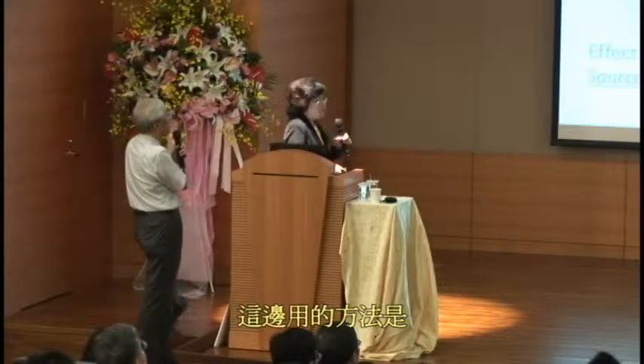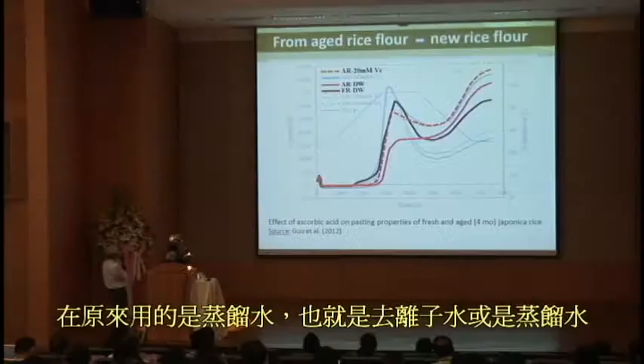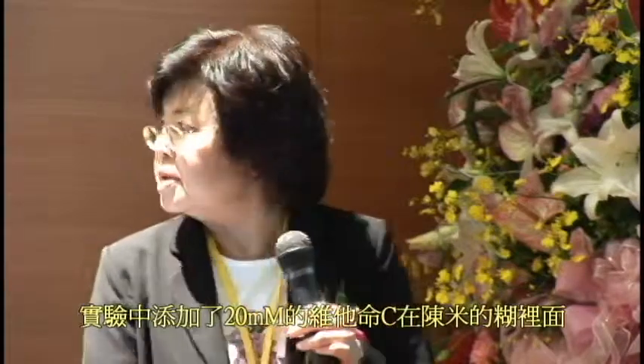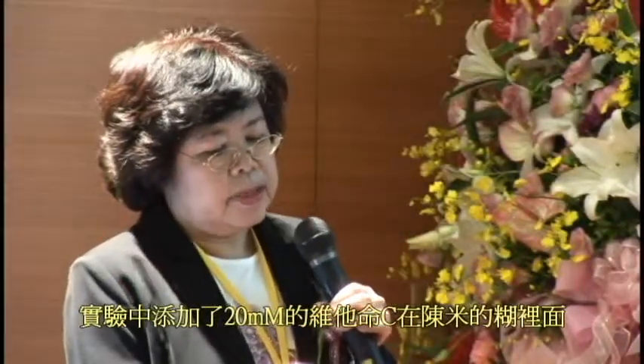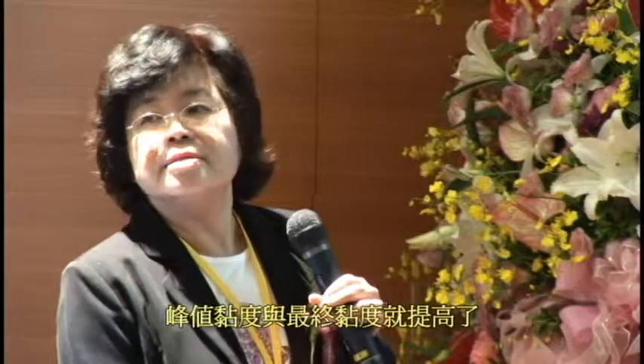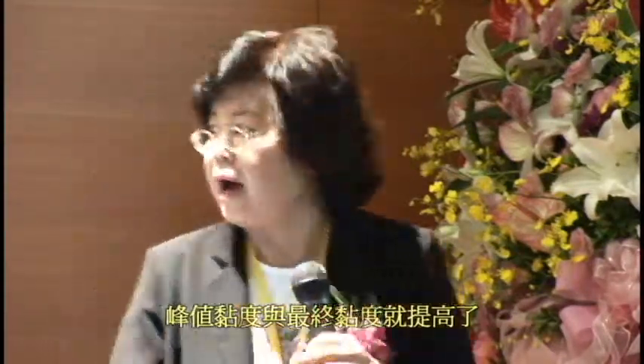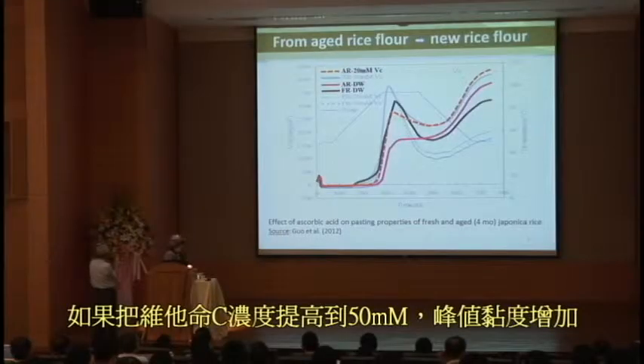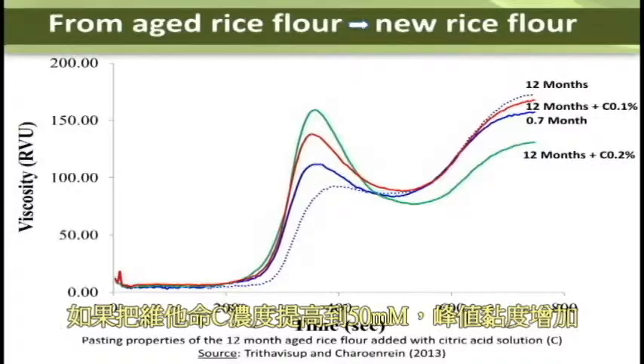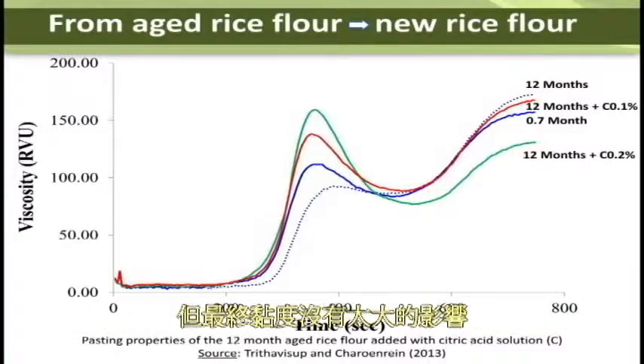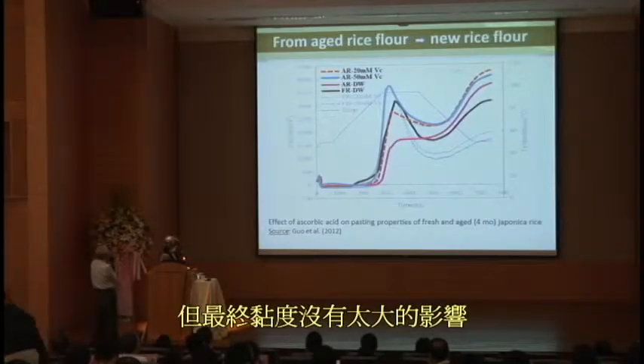Okay, so this is what they found. They used the aged rice, the pink one, the same one, but instead of using distilled water, they used 20 millimolar ascorbic acid solution. You can see that the peak viscosity increased from this one to this one, so it's higher, close to the new rice. When they increased the concentration of the ascorbic acid to 50 millimolar, the peak viscosity increased, but the final viscosity didn't move down.